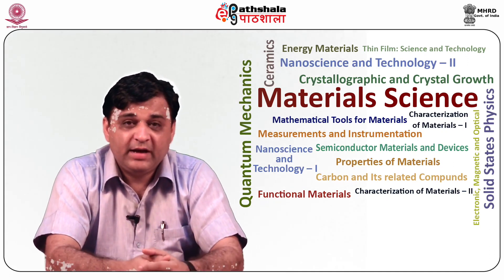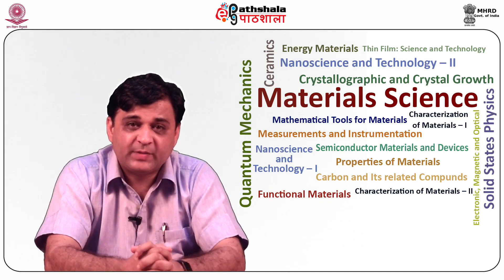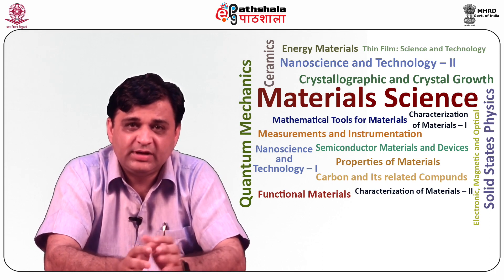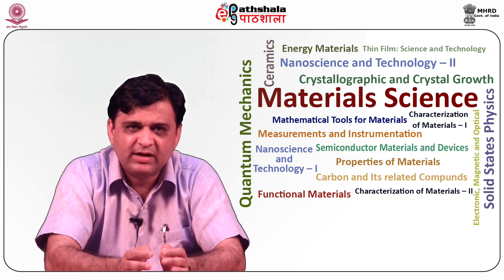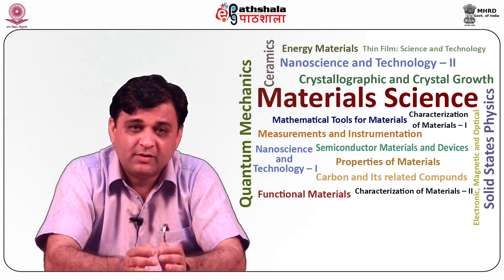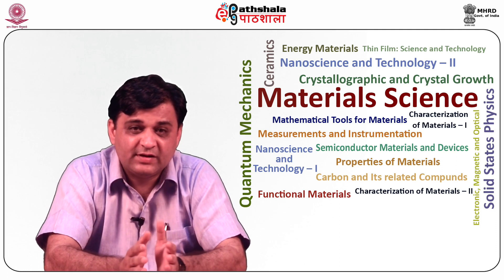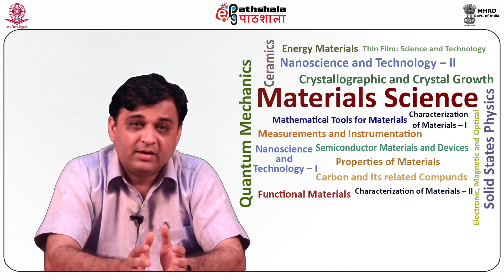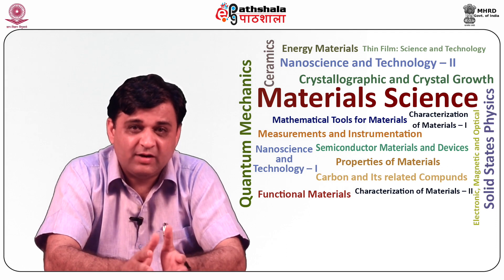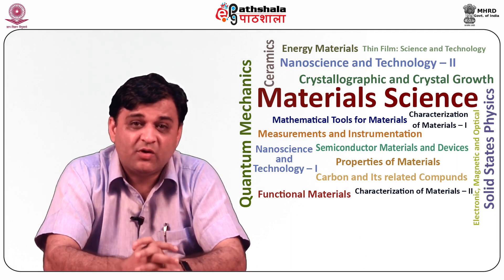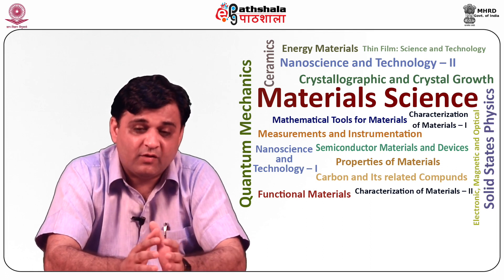Now let us talk about the advantages of x-ray reflectivity. It gives information on film thickness, electron density profile along the vertical direction, and average roughness of the surface. It can measure thickness with very high precision, of the order of 2 angstrom. We can also determine the electron density profile of multilayers and roughnesses of buried interfaces from this analysis.